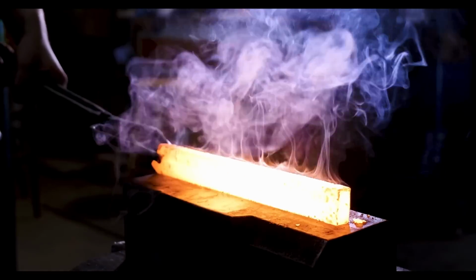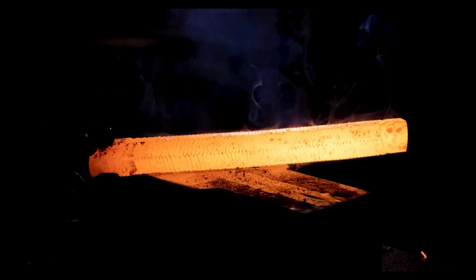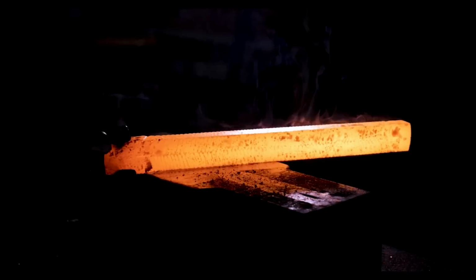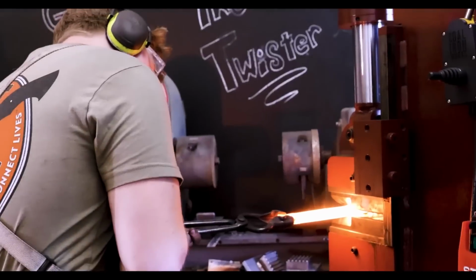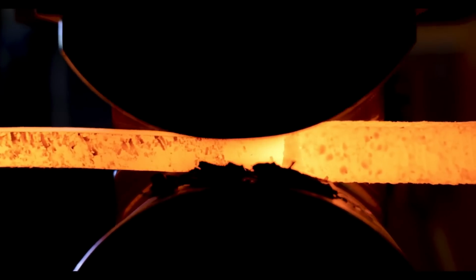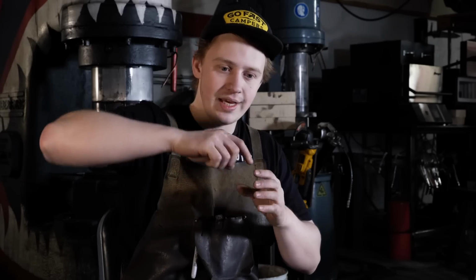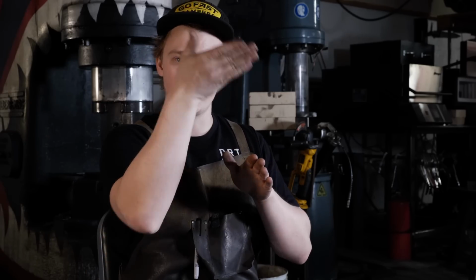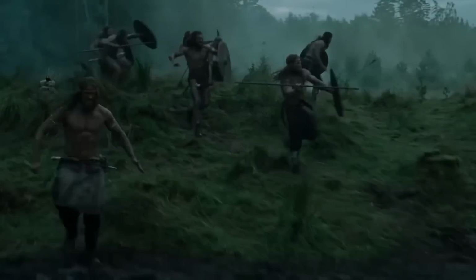Now, a really common historic method was to twist multiple bars of steel and then forge weld them together and then grind it down, and what you're left with is a really nice pattern that if you do it properly can line up with itself. It's very visually appealing, and it's a really neat way to not only strengthen the material because you're mixing it so that the forge weld lines are no longer just straight sideways on the material, but they're wrapped around, and so it can kind of really help strengthen that pattern. That's not a big consideration nowadays because our forge welds are so good, but back in the day that could be really helpful for building a sword that needs to hold up to raiding English villages and stuff like that.